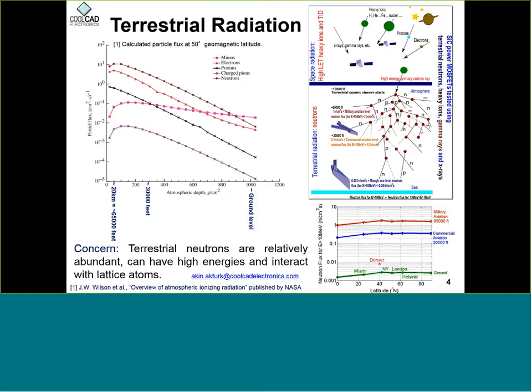The neutron flux usually reaches peak value at around 60 or 65,000 feet. It's about 20 kilometers altitude. And it drops roughly an order of magnitude when the altitude is half of this, at 30,000 feet. And at ground level, it drops by another roughly 2 orders of magnitude. So at sea level, you have high energy neutrons with a flux of roughly 0.001 neutrons per centimeter square per second. So these are very high energy neutrons, and they can cause upsets.